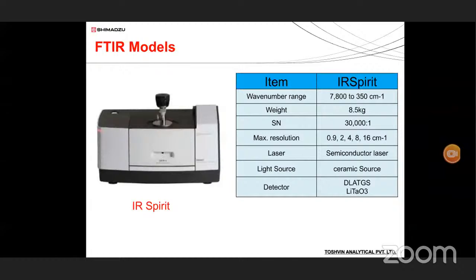But whenever you are using the FTIR, we ensure that a few precautions are taken, like humidity and temperature. The humidity for all these FTIRs should not be more than 60, and the temperature should be around ambient, or below 24 degrees Celsius. 21 to 24 degrees Celsius is sufficient for the FTIR instrument. So take care that the humidity does not exceed. If the humidity exceeds, it will affect the beam splitter, because the main heart of the FTIR is the beam splitter.